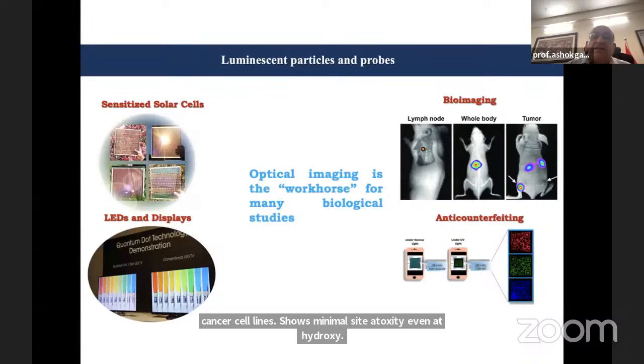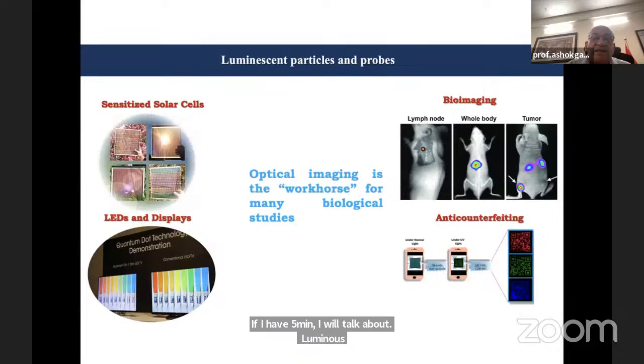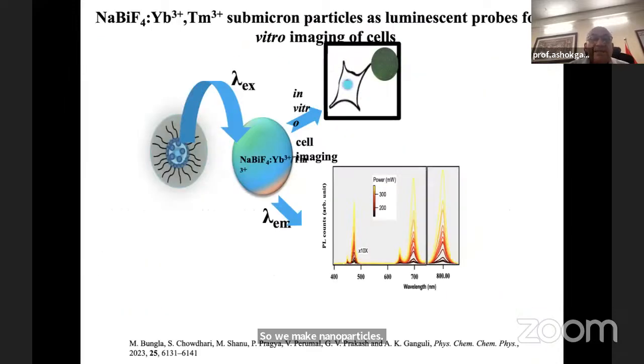If I have 5 minutes, I will talk about luminescent nanoparticles, which is another area, more for imaging. So we make nanoparticles of this kind. If you can see, this is using rare earth ions. You know, rare earth ions from chemistry we know have f-f transitions which give out light. So once this particle is in the cell, it can emit light, which we can see for imaging. So the particle that you make should not be toxic. So we chose a sodium bismuth fluoride based particle, which is very new.